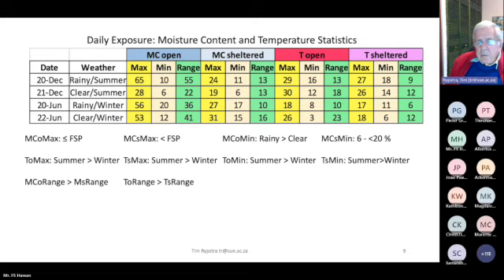And then one could also say that the minimum moisture contents on the rainy day, as one would expect, are higher than on a clear day, and the minimums for the sheltered one vary between 6 and less than 20. So with this we can get an idea of what levels these moisture contents are changing on a daily basis. And at the bottom, the outside range is normally larger than the sheltered range for the moisture content, but also for the temperature. Okay, the next slide, please.